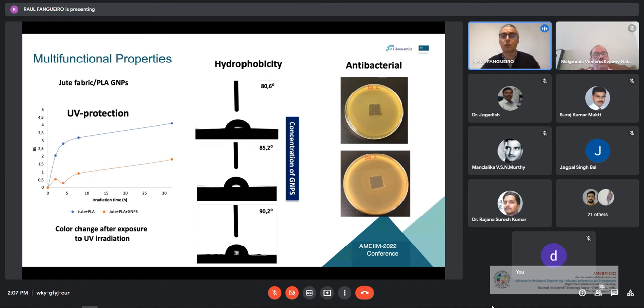But we can also control the hydrophobicity of the material, so this surface characteristic of absorption of a drop of water or liquids, we can also tailor these properties, this response of the surface of the material, and then based on that, change the hydrophobicity or the hydrophilicity of the material, and of course based again on the graphene nanoparticles we are using. We can give also the antibacterial characteristic to the material.